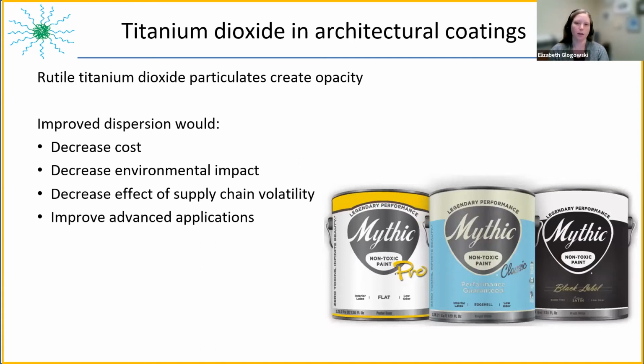So what problem are we trying to solve specifically? A major component of an architectural coating is the titanium dioxide pigment. And so the titanium dioxide is necessary to get the opacity or coverage of the coating. And so the better dispersed the titanium dioxide is, the more effective the coating will be. And the better dispersed it is, the less titanium dioxide we need to add. So of course, if we need less titanium dioxide, that means the cost is less for this component. The environmental impact is less because there's an environmental cost for producing the titanium dioxide.